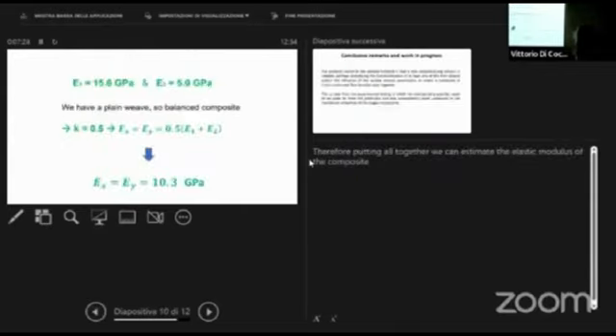Given all these parameters, and setting these parameters inside of the simple model that I showed before, we may obtain the theoretical stiffness that we have to obtain in both directions, transverse and longitudinal, that is 10 gigapascal, if we take into account the characteristics of the matrix and the fibers. And we remember that the experimental value is lower, so there is a discrepancy, but this is expected, and this is the challenge that we have to face.